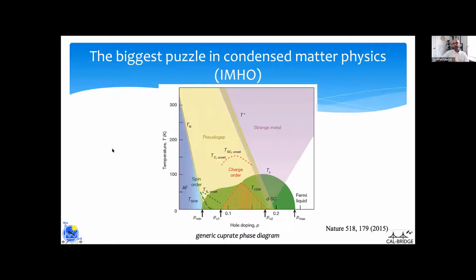But it turns out that if you take these materials and you dope, you introduce something called a hole. So you basically change the chemical formula. Let's keep it simple. If you change the chemical formula of the material, you end up with something like this that is called a phase diagram. A phase diagram shows you temperature and this amount of chemical disorder, chemical doping, if you will, just to give you some easy to grasp perspective here. And what you see here is, for example, this green dome here is the superconducting dome, where you basically have a TC, and the material is only superconducting for a certain composition, basically, below a certain temperature, okay?